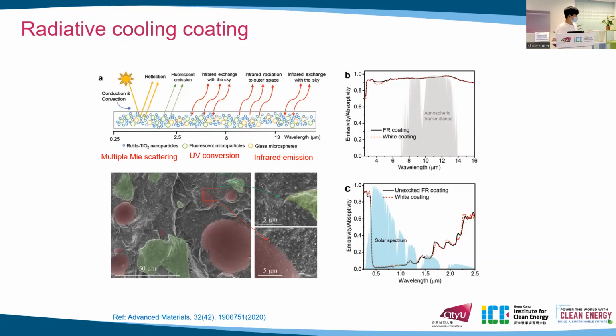As we said before, below 90%, it cannot reach sub-ambient cooling. So we added some fluorescent pigment to compete with TiO2 on its UV absorption and convert some part of the UV absorption to re-emitted visible light. Then the solar reflectance can be increased to over 90%. Further, we add some glass microspheres because they have intrinsic resonance at wavelengths around 10 micrometers, so they can efficiently improve the infrared emission.